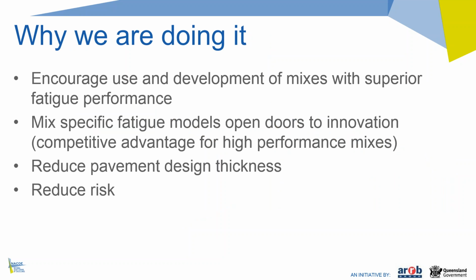Why will we be doing that? Well, we want to encourage the use and development of mixes with superior fatigue performance, and think, for instance, of EME2. Mix-specific fatigue models also open the doors to innovation, so it will now be possible to develop your own mixes with superior fatigue performance and characterize them and use them directly in pavement design, which then, of course, hopefully will again lead to reduced pavement thickness, and as a result save the taxpayer money. And in my opinion, this will again reduce risk, because instead of using a general model that was based on the mean performance of 12 mixes tested overseas, we will now be using models that were specifically developed for Australian mixes.